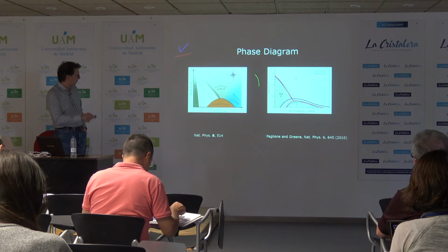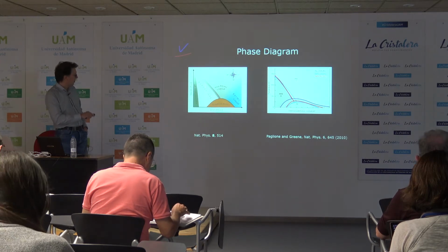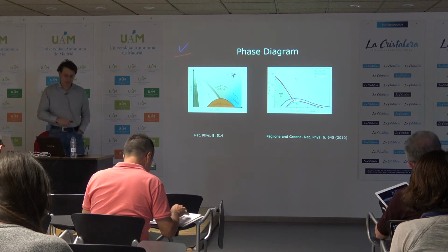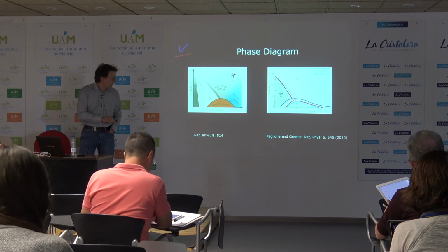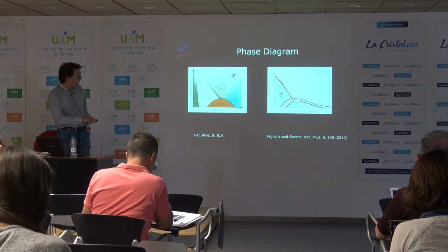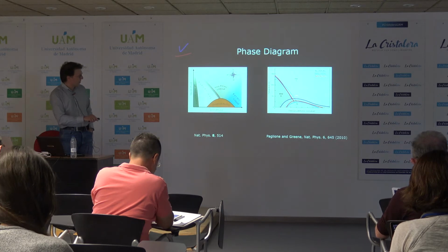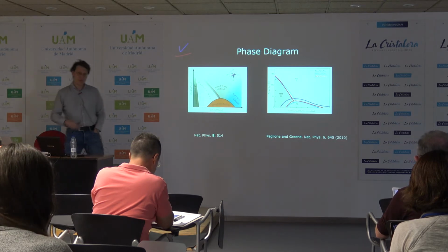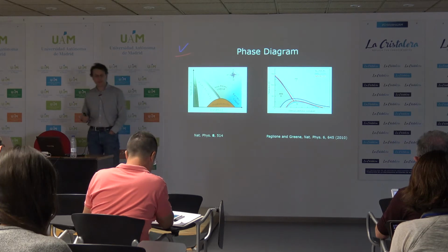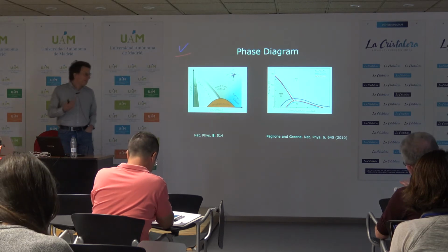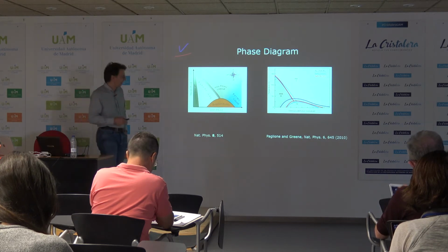so here in the phase diagram for the cuprates, you have an antiferromagnetic Mott insulator at zero doping, the mysterious pseudogap phase in between, and then superconductivity emergent. In the iron-based superconductors, a magnetostructural phase transition is suppressed, and the suppression appears to happen right where you have the optimal doping for superconductivity. So this tells you that somehow superconductivity and magnetism in these materials are intimately related.